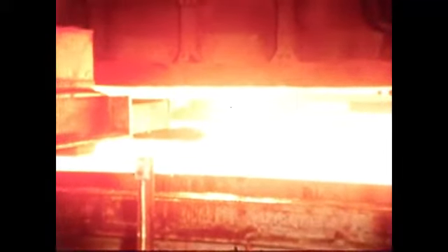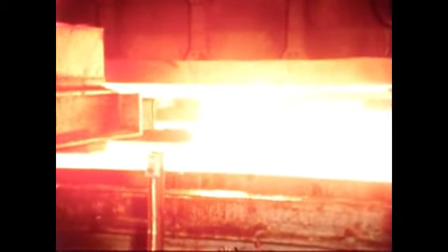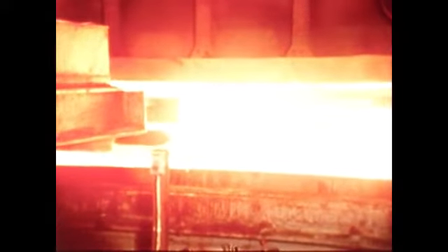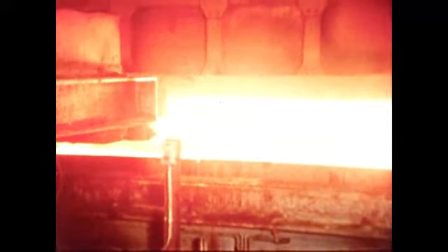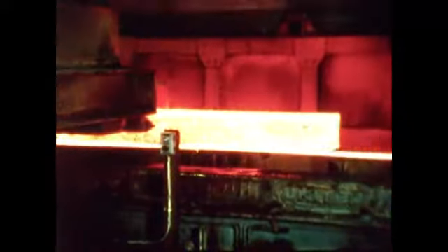At the exit end of the furnace, blooms emerge into the rail mill at a steady production rate, while others are being charged into the furnace behind them. Only capability like this can make Wheeling-Pittsburgh's rail production capacity possible, up to 400,000 tons per year. The bloom is removed to a roller line and sent through a descaler to eliminate furnace-induced scale buildup and assure a maximum quality finish.